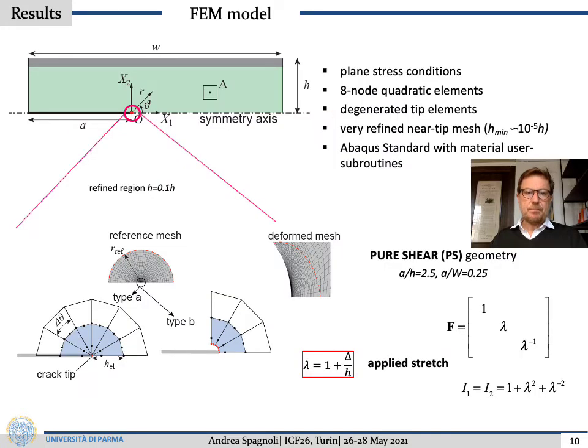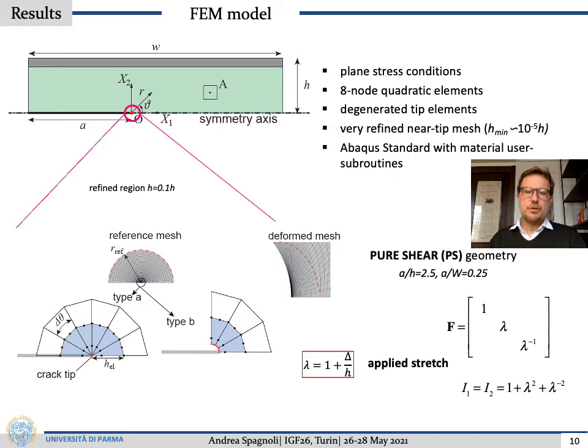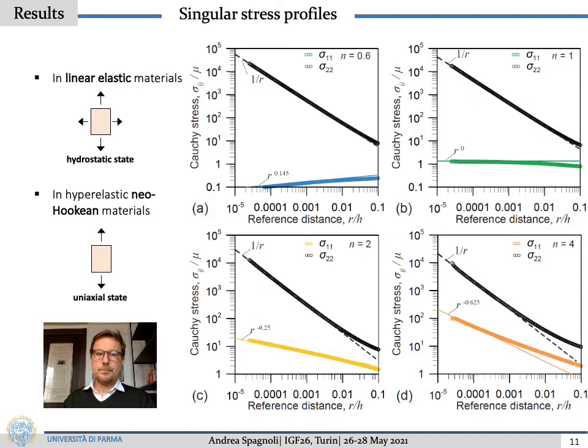We have performed finite element analysis, making detailed models where the region near the crack-tip is very well refined. We are studying the pure shear geometry, and here are the details of the mesh we used. We applied a uniaxial stretch to the model. Here are some results in terms of the singular stress fields near the crack-tip, and we can see very good matching with the analytical solutions.